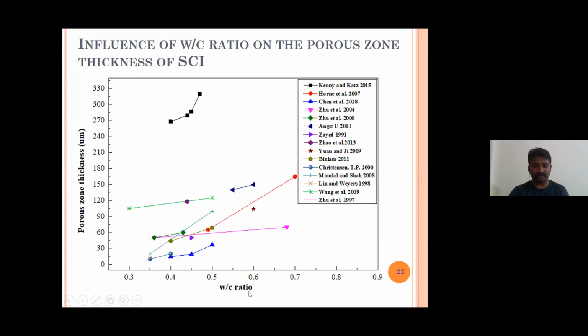So what happens to the porous zone thickness at the steel concrete interface if the water cement ratio increases? As you can see, all the lines are going above. As the water cement ratio increases, the porous zone thickness at the steel concrete interface is increasing. Can you see that part? As the water cement ratio increases from 0.4 to 0.5, the porous zone thickness is increasing up to 300 micrometers. Okay, fine. So this is the literature data.